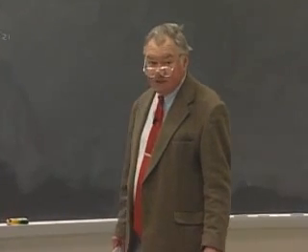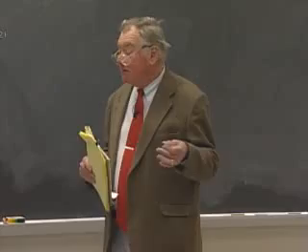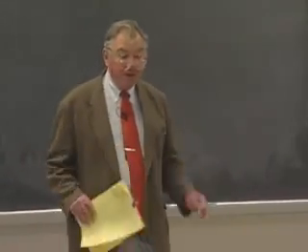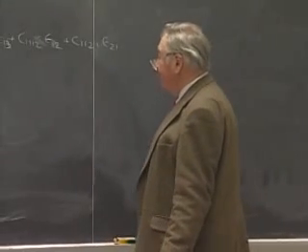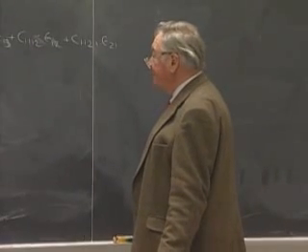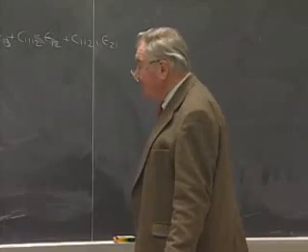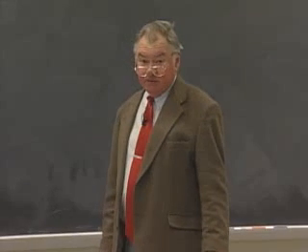And you might want to do that for practical reasons, such as cutting out a specimen, which makes it convenient to define the stiffnesses and compliances relative to a coordinate system taken along the logical directions in the specimen. And the other reason for doing it, and that is what I want to do a little bit of this afternoon, is to derive the symmetry restrictions on the stiffnesses and compliances.